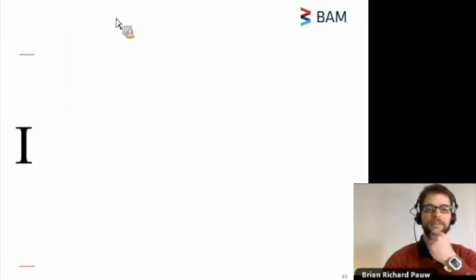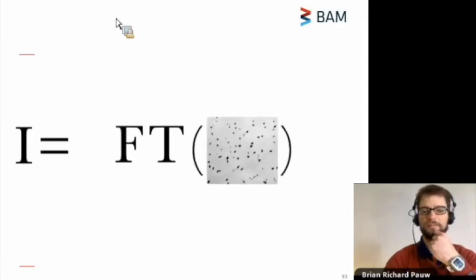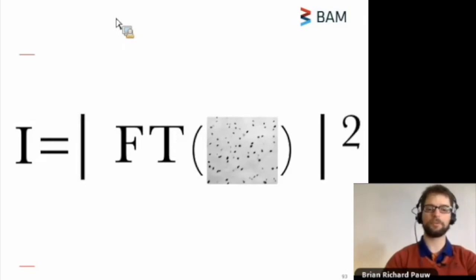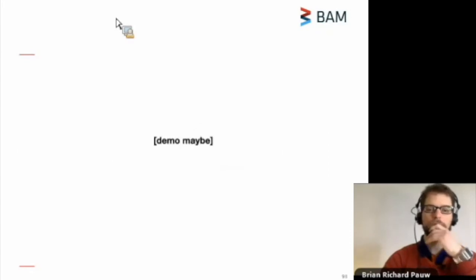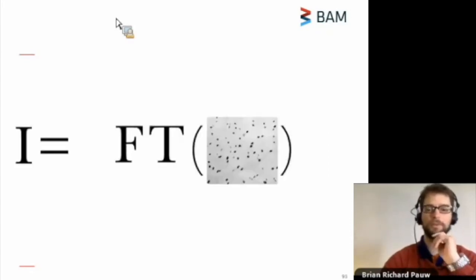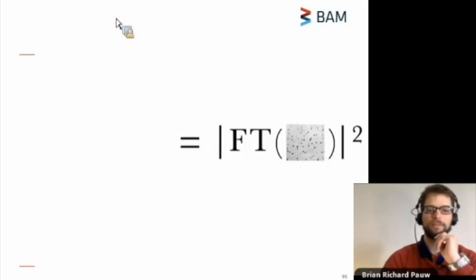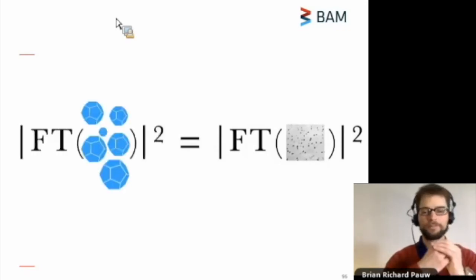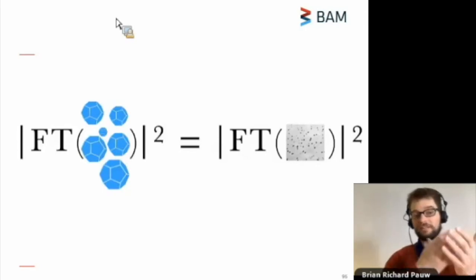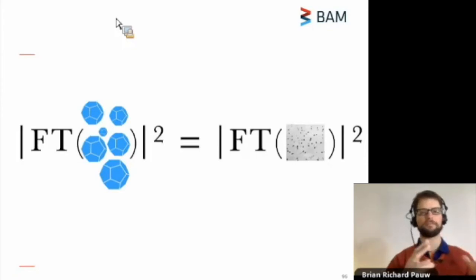Just to recap, the intensity is our Fourier transform of our electron density map, but only the intensity component, not the phase component. So what can we do to analyze, to describe the electron density here? Or to get some information on our structure back? Well, there's one thing we can do. Since we know it's a Fourier transform, we can compare the measured intensity to a Fourier transform of a model structure. And by systematically adjusting these model parameters, we can get a better and better match between the model intensity and the intensity from our data.